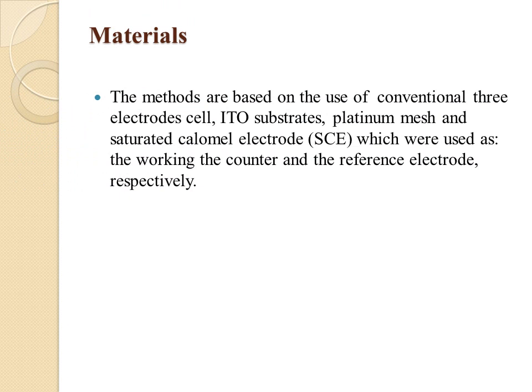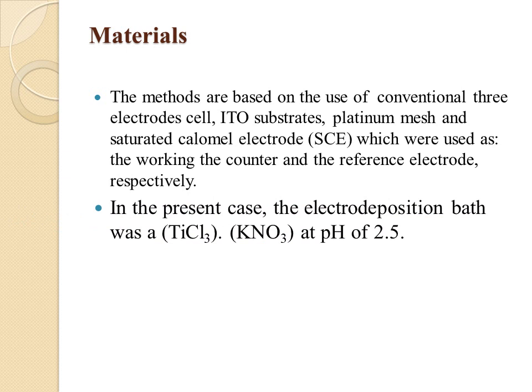The methods are based on the use of a conventional three-electrode cell: ITO substrates, platinum mesh, and saturated calomel electrode, which were used as the working, the counter, and the reference electrode respectively. In the present case, the electrodeposition bath was TiCl3 and KNO3 at pH of 2.5.